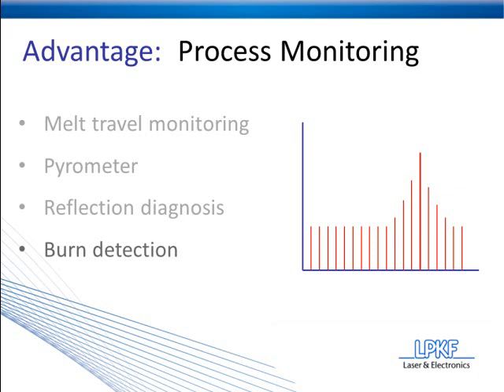Now, two reasons a burn can take place. One is if a laser is left on a piece of plastic for too long, it's going to essentially vaporize the plastic and cause a heat flash, which is kind of what you can see here with this little spike. The second way you'll see a burn take place during the process is if there's a contamination on top of or within the plastic. When the laser strikes this, it's going to burn it, and that burn will create another heat flash, and you'll see that reflected in the burn detection system.